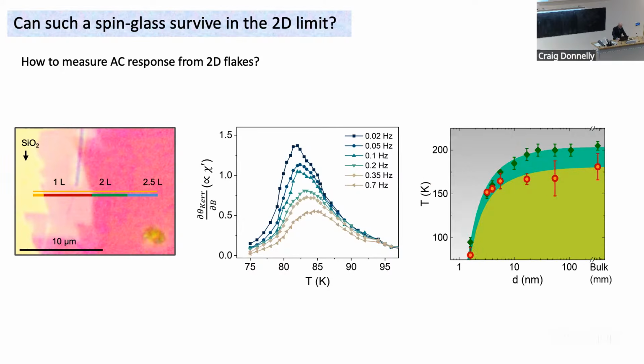So we think this is very good evidence that this flake, just one monolayer thick, exhibits a spin glass, the first two-dimensional spin glass. And here, from the temperature-thickness phase diagram of the flake, what we see is the green curve. The green dots correspond to the ordering of the ferromagnetic layers themselves. And a few degrees below that, we see this evidence for spin glass freezing of the moments within the van der Waals layer. And of course, you can also see here that the magnetic ordering temperature of the bulk decreases significantly as we go from bulk down to a single monolayer, shown here.